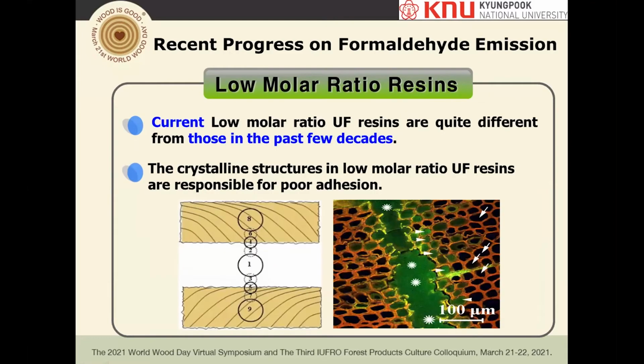So how are we going to do this? What I'm saying is the current low molar ratio resins are quite different from those used in the past few decades. The crystal structure in low molar ratio resins is responsible for the poor performance. Instead of building a three-dimensional structure, which gives strength in the polymer, they have a crystal structure. That means low molar ratio resins have poor cohesion in bond lines.